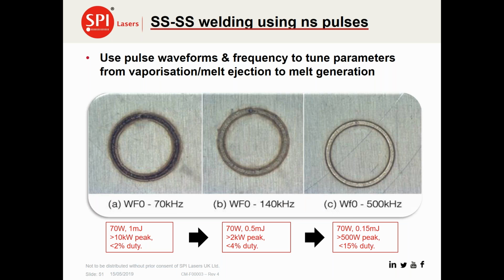What you actually see here on the left is a 70-watt laser at maximum pulse energy, at maximum peak power. And what we're seeing is lots of oxidization. It's almost starting to cut through the material itself. However, if you then back off on the pulse energy and the peak power and optimize the duty cycle so that you deliver the heat input and really control that heat input, then you start to get a better weld. And by the time you get to this image on the right, where we have optimized the pulse energy, the peak power, and the duty cycle, we come up with a rather nice looking weld, which has pretty good quality in terms of strength and other properties.